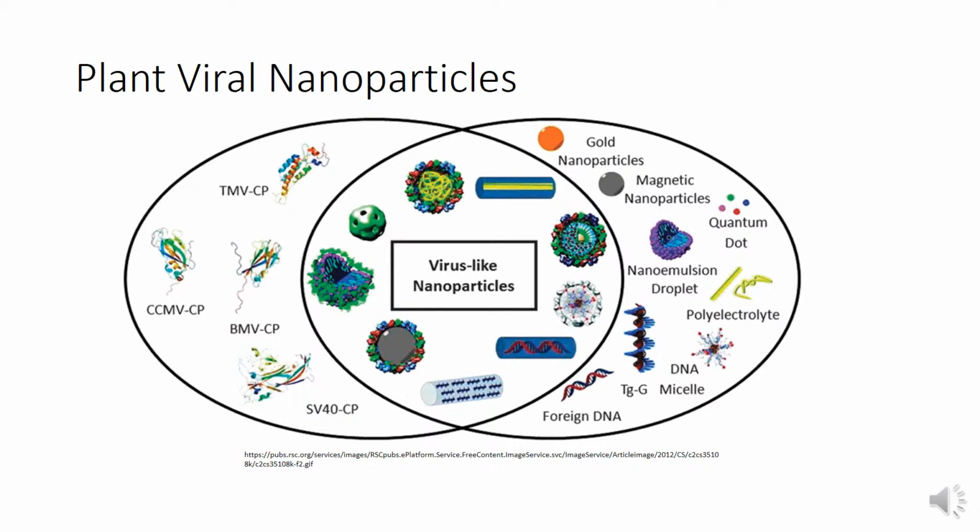These plant viral nanoparticles seem to offer a solution to the low aspect and biocompatibility issues that come with other nanoparticles. They have already been established to have the ability to develop gene therapy vectors, vaccines, and oncolytic viral therapies. Plant-based viral nanoparticles in particular are attractive because they have been shown to be non-pathogenic in mammals. Additional advantages include a diversity in size and shape, being truly monodisperse, meaning that they are of uniform size, highly symmetrical, and having a structure known down to atomic precision. All of these allow for an appealing target to engineer nanoparticles with features for targeting ligands, drugs, or imaging molecules.